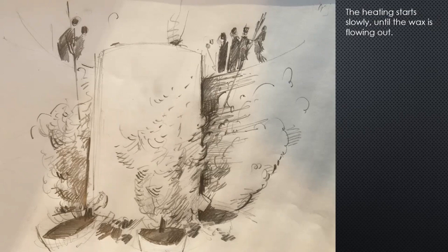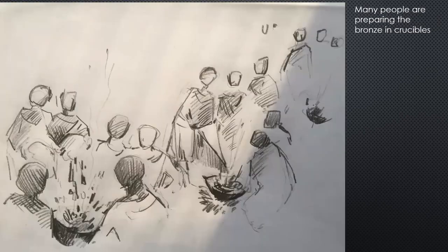Firewood was stacked all around the mold, lighted and stoked repeatedly. The mold was completely fired when no vapor rose from the funnels and air vents anymore. In the meantime, another part of the casters, together with numerous day laborers, had begun to prepare the crucibles for melting the metal. The clay crucibles were set into flat, preheated depressions that were filled with charcoal.